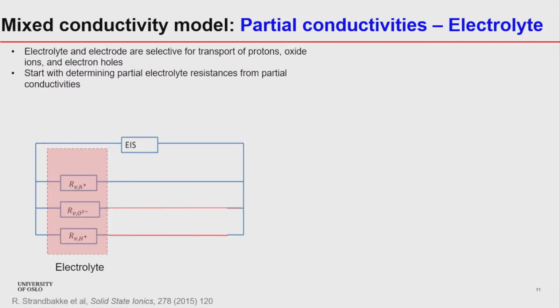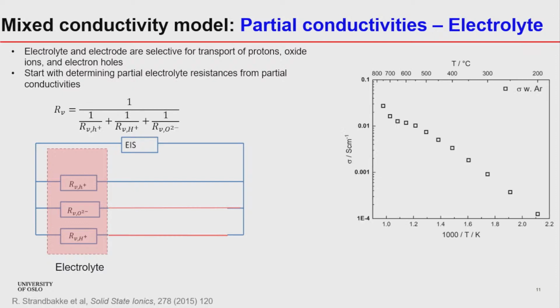So this is a very simple rail model where we show that the electrolyte resistance of the protons, oxide ions, and holes are connected in parallel. And then we can calculate the resistance for this system via this equation. And we can model the data, but the first step to model the data is to do an experiment in wet argon. So this is the conductivity versus temperature in wet argon atmosphere.